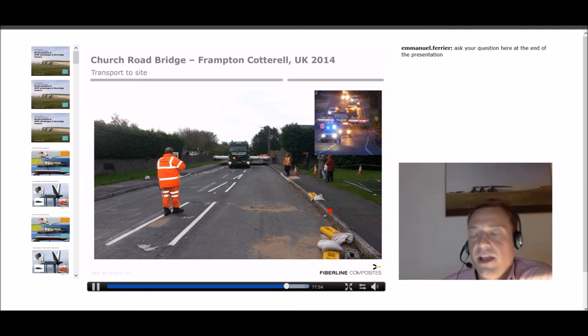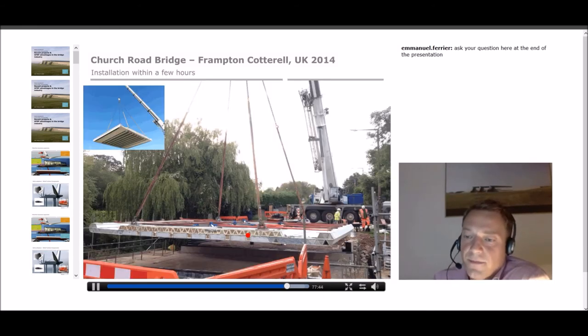For the rebars, where you put them into concrete, we are using a vinyl ester, which is a different polyester, which is of course alkali resistant. But never embed isophthalic polyester into concrete. After 10 years, you won't see FRP anymore. Believe me.